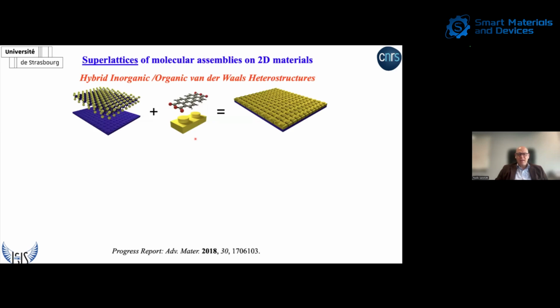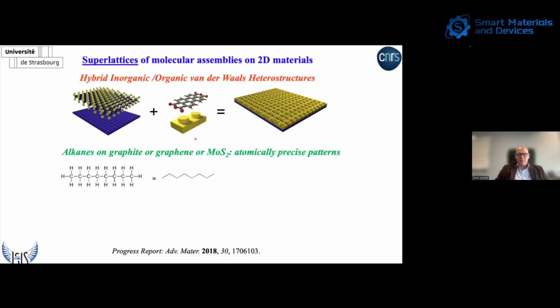And so you can actually play LEGO. Playing LEGO means that you have the two-dimensional material that is your base, your playground, and then you have your molecular bricks, and you have to find, let's say, supramolecular approaches in order to align your bricks and make them form a kind of superlattice on top of the two-dimensional material. Now, how can you do that? That is pretty simple, actually. Let's start by considering a two-dimensional material being graphene, but it can also easily be a transition metal dichalcogenide like molybdenum disulfide. And the most simple molecules that you have in this world are alkanes.